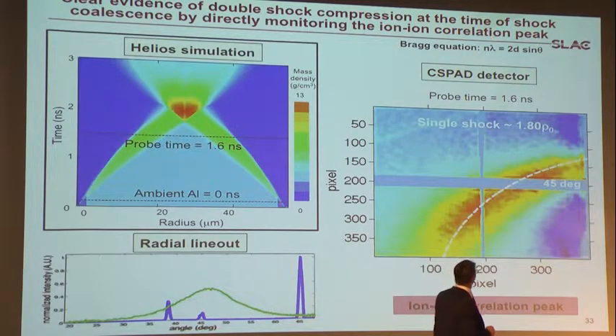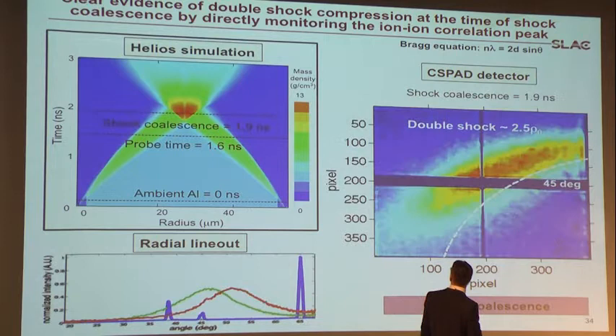So the energy of the X-ray laser is constant. That means as the density increases, the 2D gets smaller. That means the scattering angle must go up. And indeed, when we look at the shock coalescence, you see that the angle jumps up. So this is, again, a very nice measurement of mass density now.